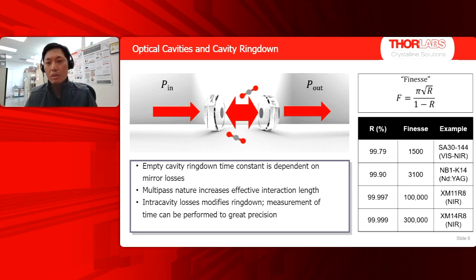And moving on to supermirror levels of performance, 99.997%, for instance, our XM11R8, gives you a finesse of 100,000. Even in our catalog, you can get these XM14R8s for 1550 use, and they're 99.999% reflective, and that gives you a finesse of 300,000. So really what I'm trying to drive home here is that supermirror levels of performance are on the order of 5 nines of reflectivity and on the order of 100,000 or more in this metric known as finesse.